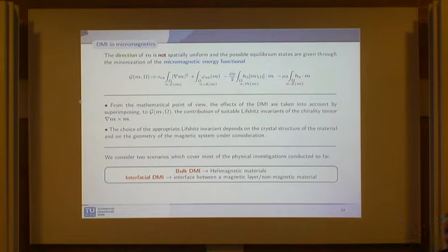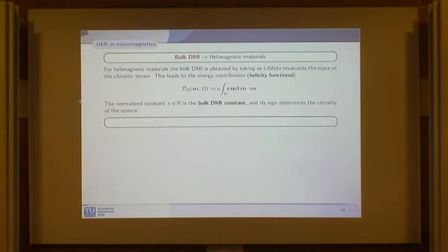say, multi-layers, and this kind of antisymmetric interaction appears at the interface between a magnetic layer and a non-magnetic material, roughly speaking. So how can we model the bulk DMI? In principle, if you take the summation that I showed you at the beginning, the discrete one, you can do some formal computation if you wish, and you will come out with this expression that you see here. So this term, curl m dot m.